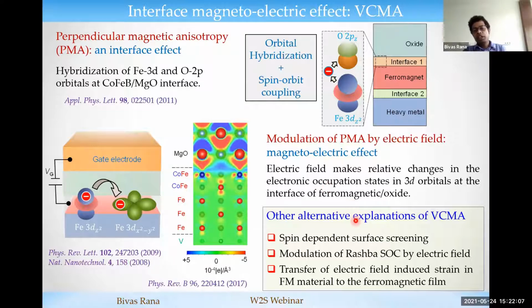Of course, there are some alternative explanations of the origin of this voltage control magnetic anisotropy. One is spin dependent surface screening. It is well known that when we apply the electric field at the metal surface, the electric field cannot penetrate more than a monolayer or so, due to the screening created by the conduction electrons. But the situation is different for the ferromagnet, because in the ferromagnet, the spins are polarized. The number of up spins is different from the down spins. That's why this polarized spin induces some magnetic moment. That's how you can change the total magnetization of the system.